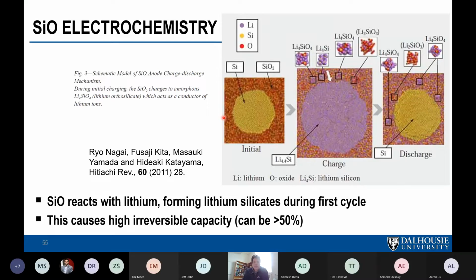When you lithiate SiO, the silicon oxide regions lithiate first because lithium more strongly bonds to oxygen than to silicon, and that happens at around 0.6 to 0.7 volts, somewhere around there. You can see a little plateau in some materials where that happens, and you form a predominantly Li4SiO4, which is also a lithium ion conductor, and so that allows these completely isolated silicon regions to still get lithiated, even though they're completely isolated. And so after you make Li4SiO4, then the silicon can lithiate.